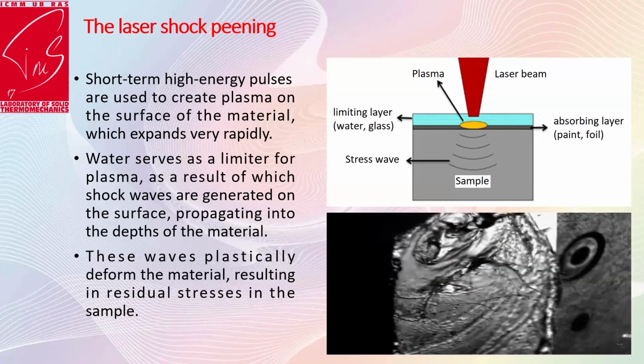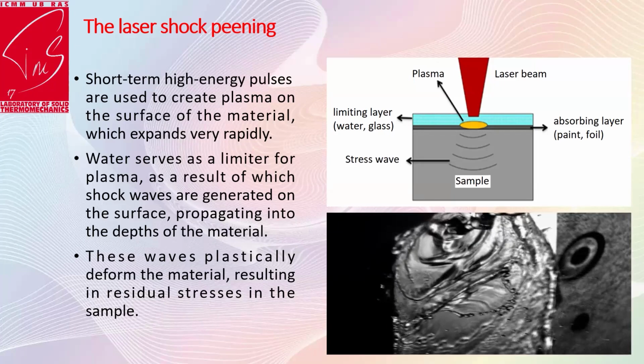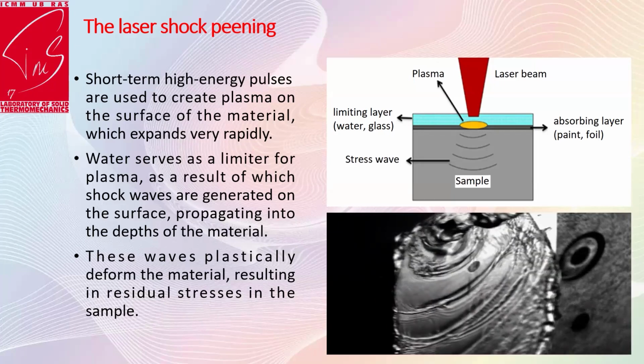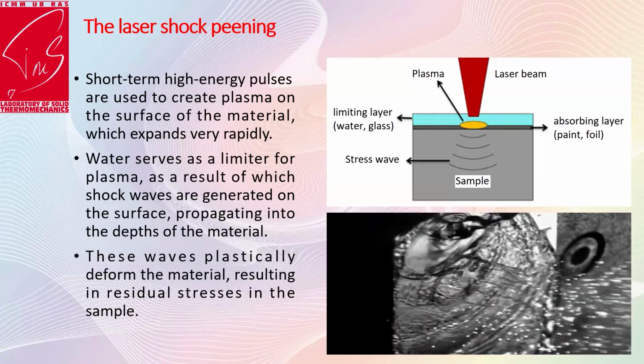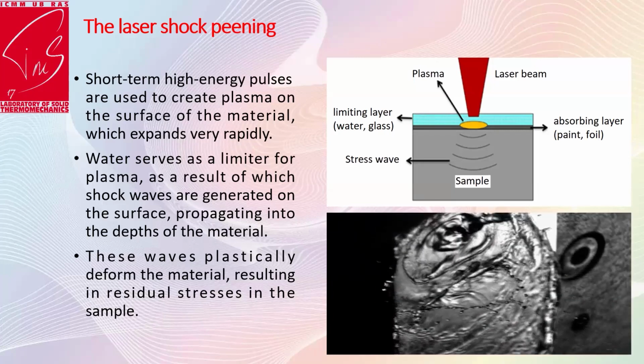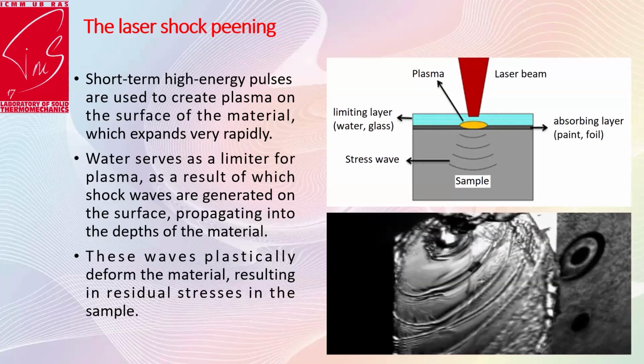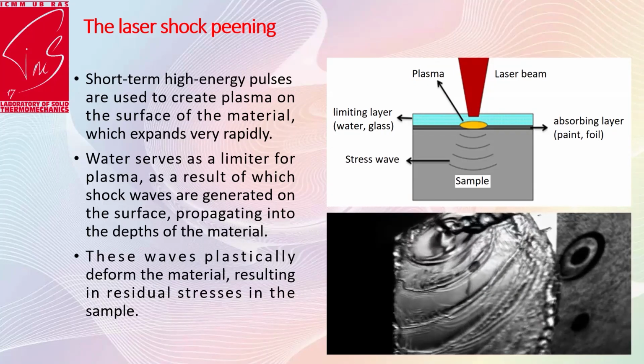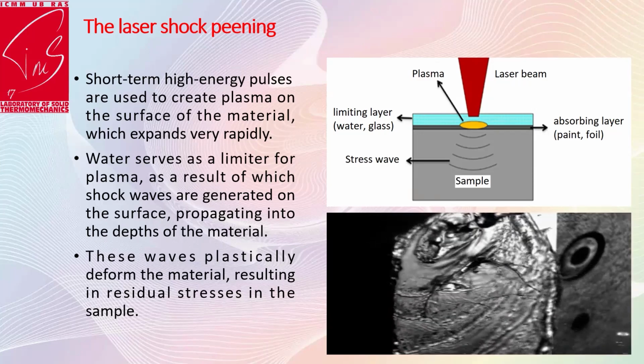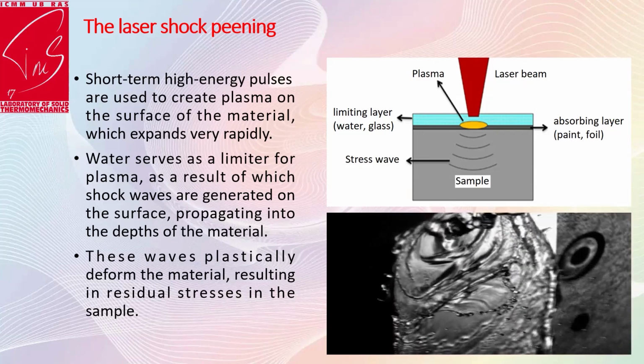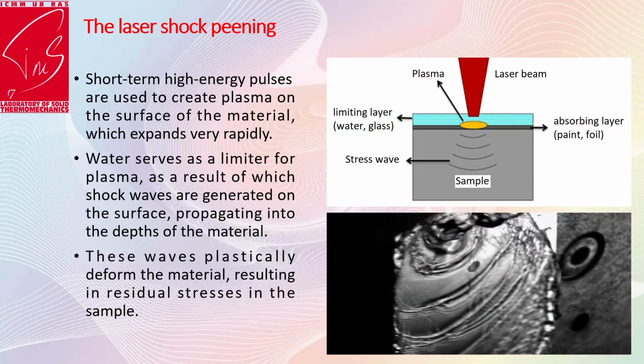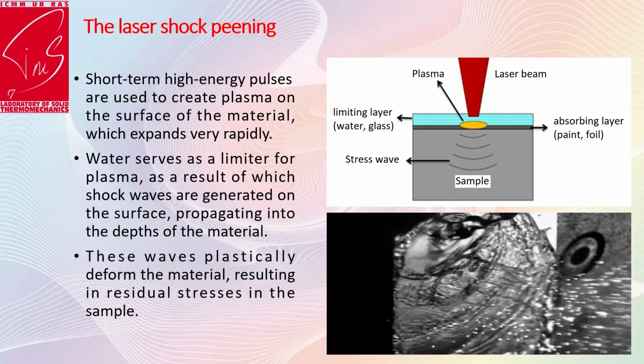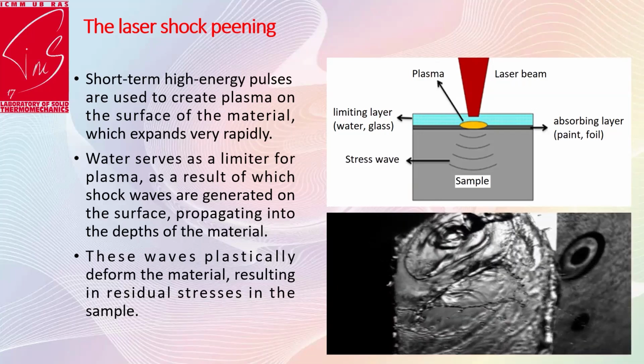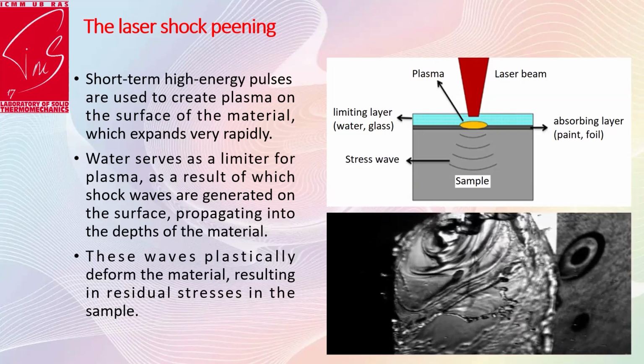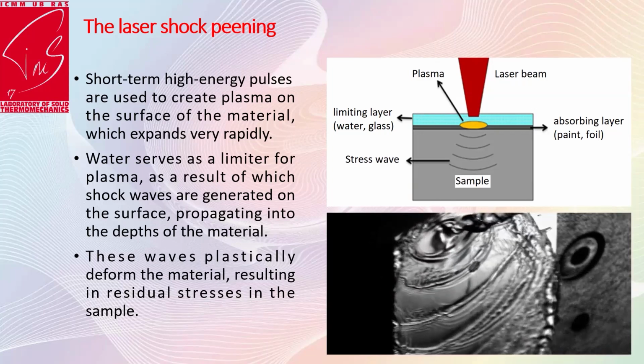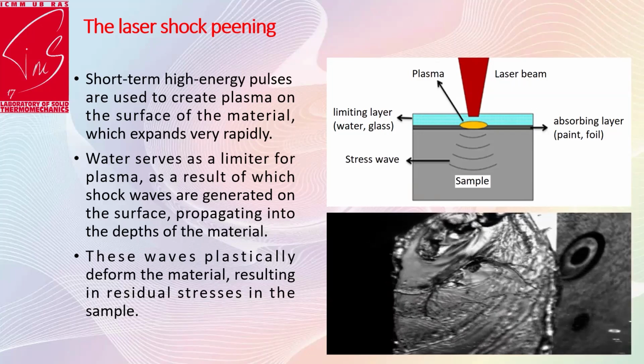Due to evaporation, you generate a shock wave, an elastoplastic wave, a very specific shock wave, with very high amplitude and very short duration. Short duration is quite important. The physical mechanisms behind the plastic deformation are quite unusual for me. This stress wave propagates in the sample, and you are able to create compressive residual stress in a depth of up to 1 to 2 millimeters.